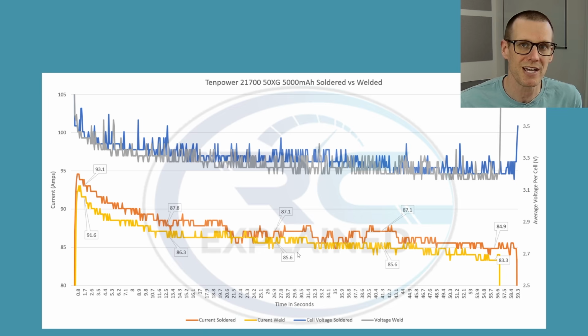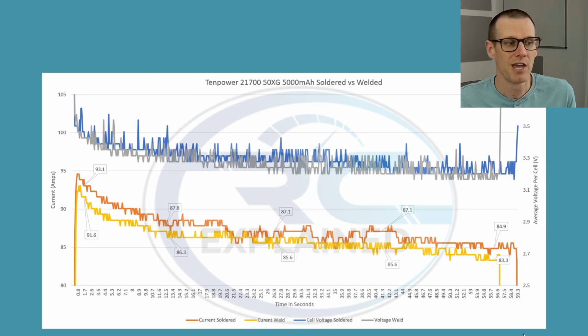And I'm most curious as to what happens with the temperature of these packs, because at the end of this 59 seconds here for the soldered pack and roughly 56 seconds, both of these packs were right up at that 70 something degrees Celsius, and the absolute cutoff is 75 degrees Celsius, where you must shut that pack down because the temperature should never push above that 75 Celsius mark. Now, typical lithium polymer battery packs, those are maxed out at around 60. So do note that it's different here with the lithium ion. The spec sheet does say 75 degrees, higher than what we're used to.